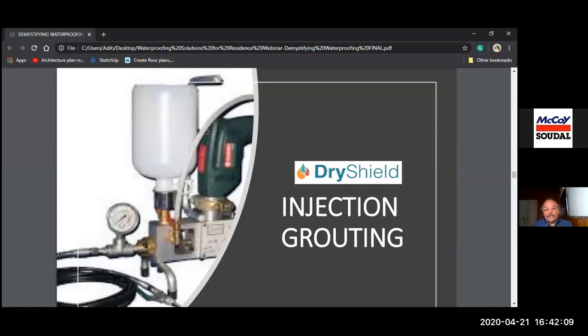You're again creating a 35 to 50 mm shotcrete wall in front of it, which has an MS welded mesh inside, which can also get corroded when water comes. The same thing, if you do it from the positive side, it will be much better. So I would recommend doing other things. There are other products which can be used. So basically for repairs, various kinds of injection groutings are used.